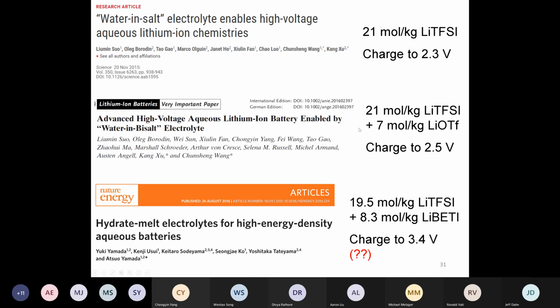After that, he also found you can put even more salt in this system. Another salt is LiOTF, and you can put 7 more molal of salt in this system, forming a 28 molal highly concentrated electrolyte. The window is slightly extended to more than 3.3 volts. The battery he used in this paper has LMO as cathode versus titanium oxide, so the battery could be charged to 2.5 volts. He called it water-in-bisalt, since it has a binary salt in it.